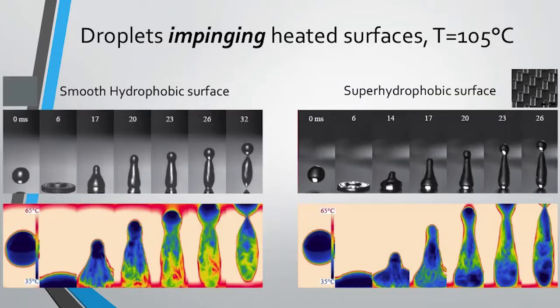But if I heat up the surface, so now I've made the surface 105 degrees C, and this is a thermal imaging camera, so it's a high-speed thermal imaging. The color blue is about 35 C, and as I go to red, it goes to 65 C. You can see as the droplet hits, it's blue and it's round. As it spreads, it's still blue, but then it starts to become yellow and red where it's in contact with the surface. That continues and goes up through the droplet. And then as soon as it's removed, it's no longer being heated. But you can see all the temperature change that's occurred in that droplet.